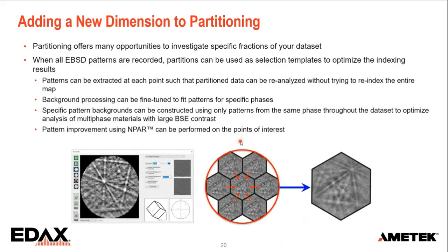On top of that, we have NPAR, and NPAR allows you to take a moving average over your data set. For each pattern, we take a look at the ring of patterns around it on our hexagonal scanning grid. We average those 7 patterns together, and then we index that pattern. And that really improves the signal-to-noise ratio, allowing successful analysis of materials that produce very poor patterns.